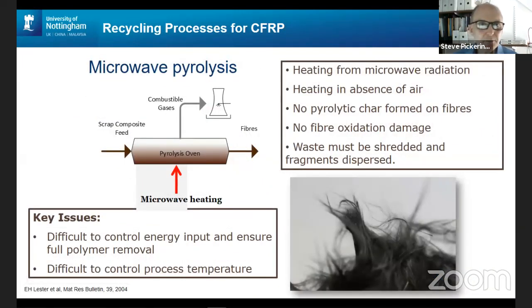The next process I'd like to mention is microwave pyrolysis. This is a variation on the pyrolysis process. Again, you're heating in the absence of air, but the heat source this time comes from microwave radiation, and it's particularly applicable for carbon fiber composites, because the carbon fibers absorb the microwave radiation, and so effectively the material is heated up from the inside. And it's been found that there's no pyrolytic char formed on the fibers when you heat with a microwave process, and so it has that advantage.